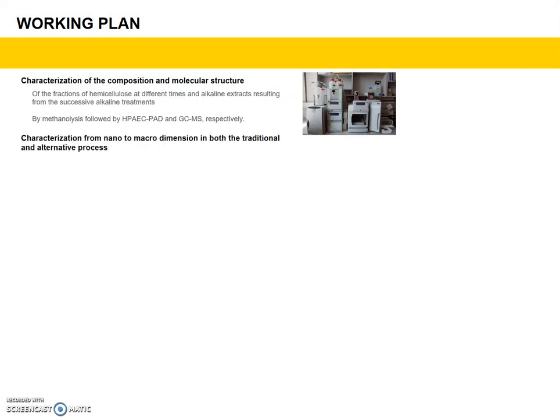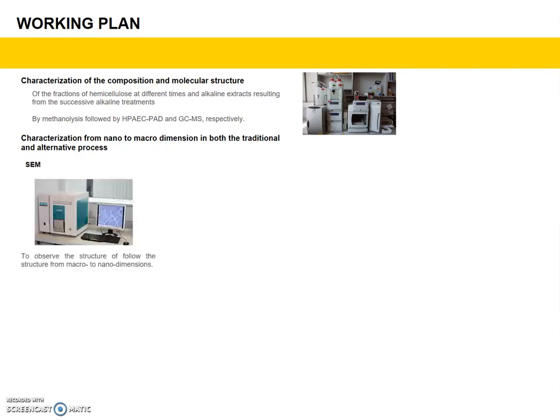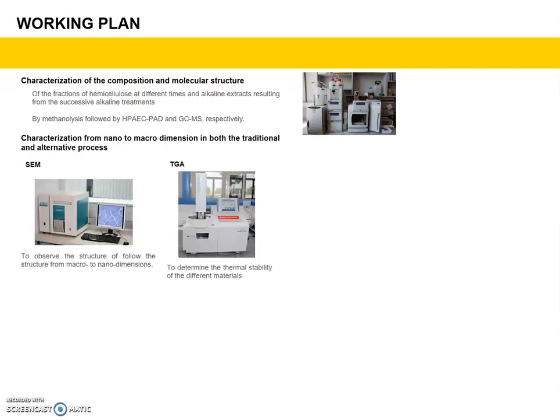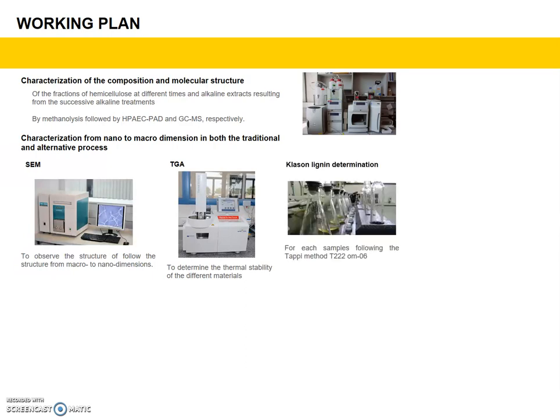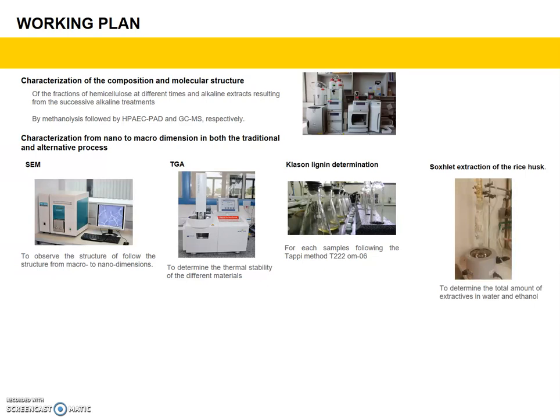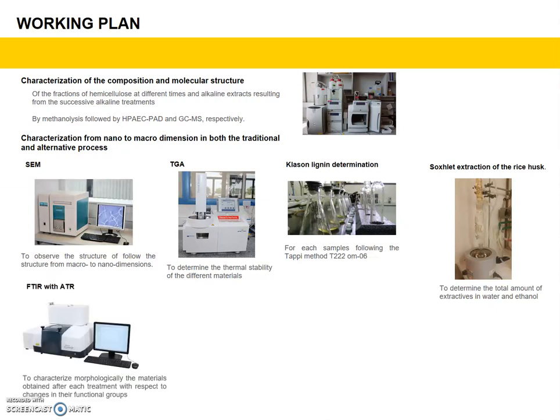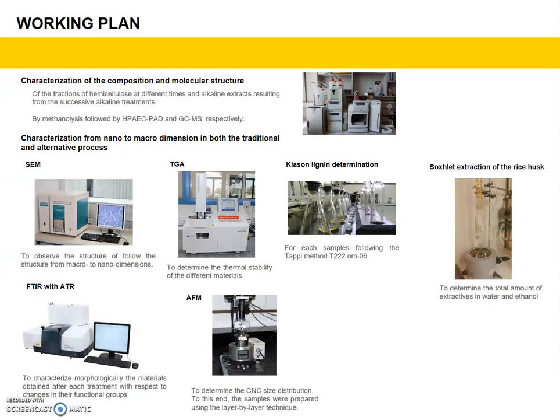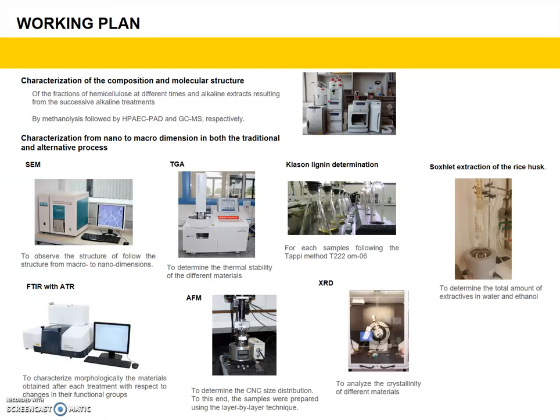In addition, the different materials obtained in both traditional and alternative processes were characterized using different techniques such as SEM to observe the microstructure, TGA to determine the thermal stability, Klason lignin determination, Soxhlet extraction to determine the total amount of extractives in water and ethanol, FTIR to characterize the materials with respect to changes in the functional groups, AFM to determine the CNC size distribution, and XRD to analyze the crystallinity.